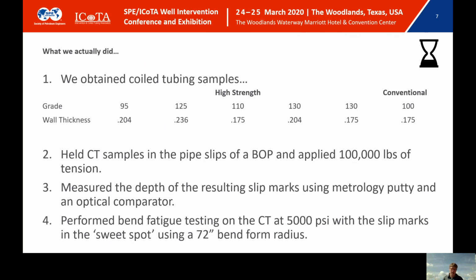We continued with our plan of pulling 100,000 pounds in. We measured the depth of the slip marks because, knowing that the wall thickness wasn't consistent from sample to sample, we tried to glean as much information from the samples as we could. And we still continued to do the bend fatigue testing at 5,000 psi on the 72-inch bend form radius.